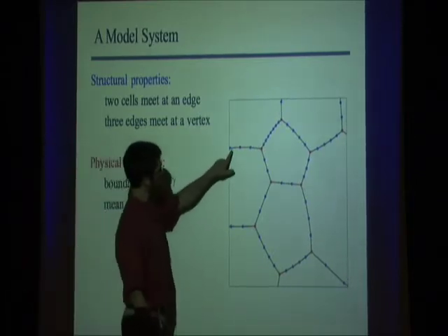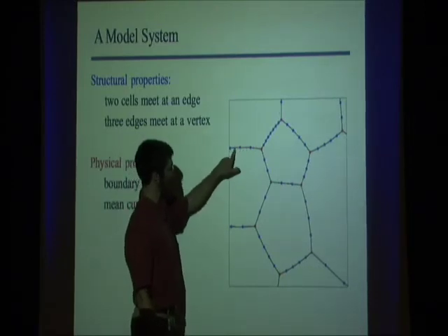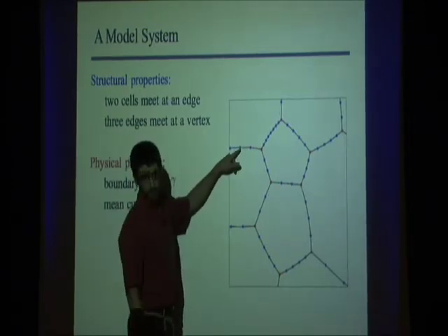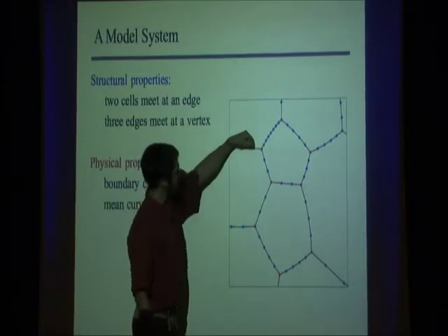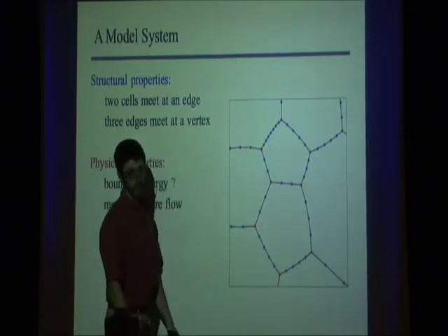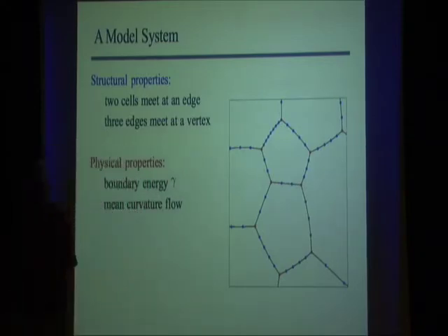So locally what you do is you approximate the curvature of this. These are obviously straight line segments, so you're looking at the turning angle. But you can imagine every point on one of these edges moving toward the center of curvature at a rate proportional to the curvature locally. And so we just let it evolve by that.